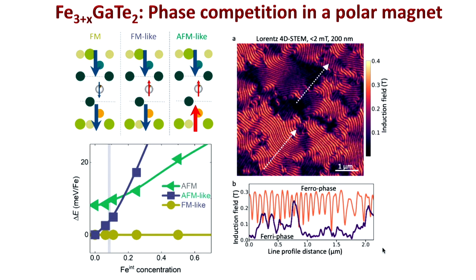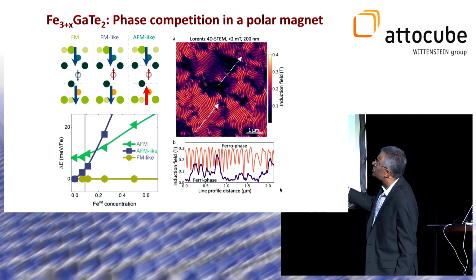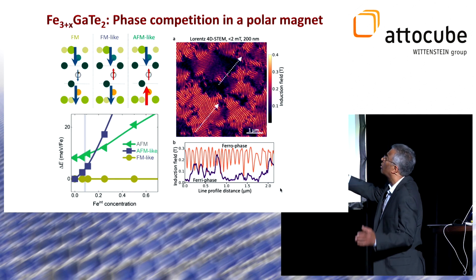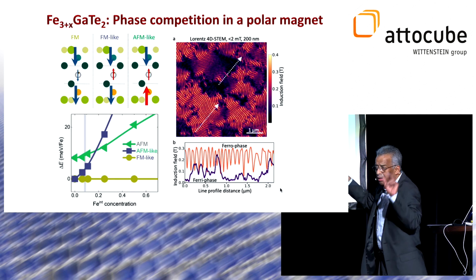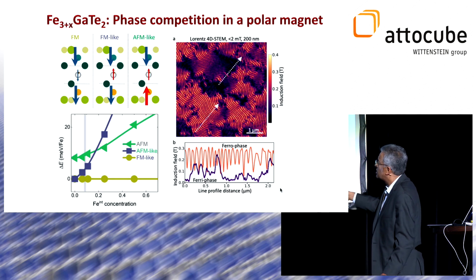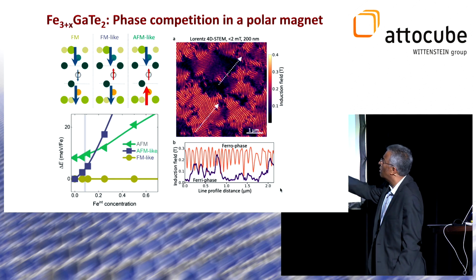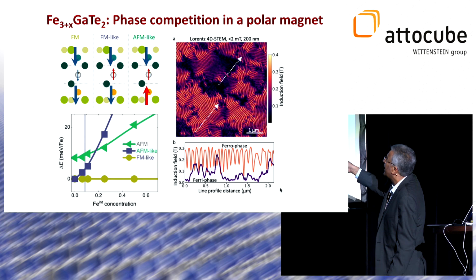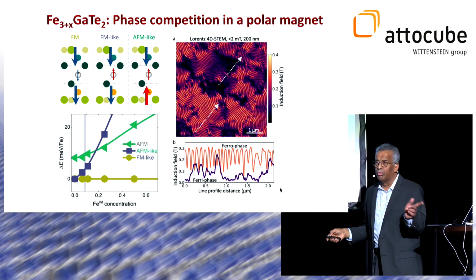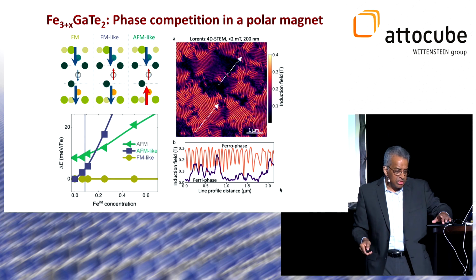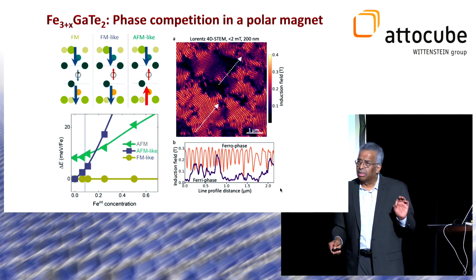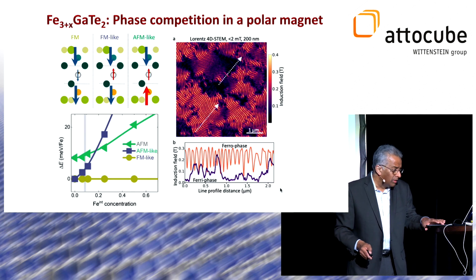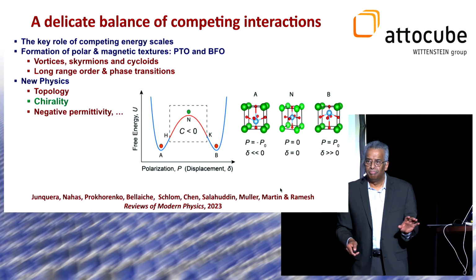So if you look at Lorentz images of this, this is the 4D STEM Lorentz image, you can actually see the coexistence of these two phases. One of them is the so-called ferromagnetic phase, in quotes. The other one is this ferrimagnetic phase, which is more like this. And so they can coexist. You can go back and forth between them. So it's telling you that at the local scale, you could have chemically driven competition.